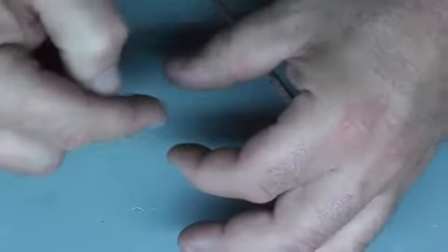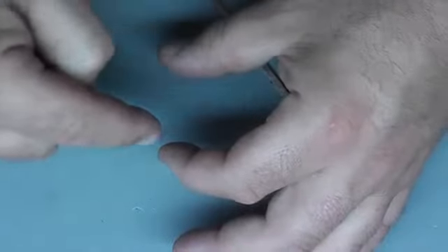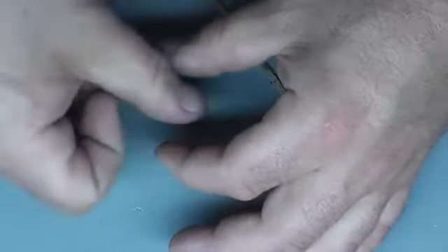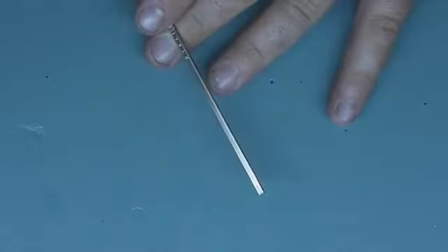So what you can actually do is squeeze it back down, and you'll have that little crack, and you can actually just braze right over it. And the good thing about that too is that's going to be the weakest point of the pipe. So if it ever does freeze up again, it's going to burst your braze joint, and it usually won't burst the pipe someplace down the line. Now we'll show examples of bridging a gap with this, and how we need to use the nitrogen and everything else.